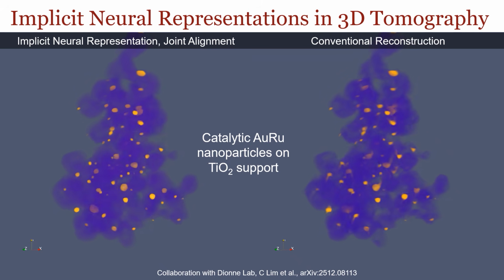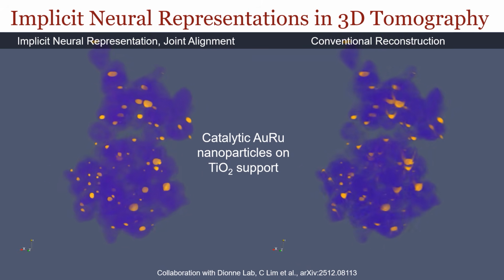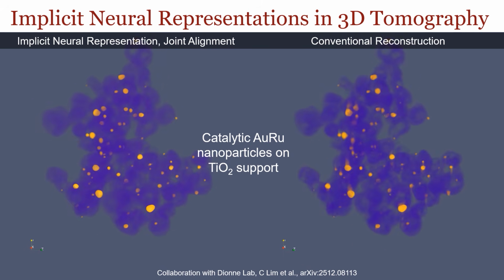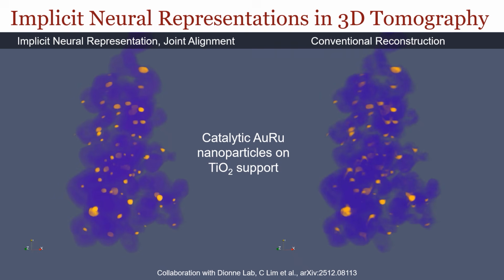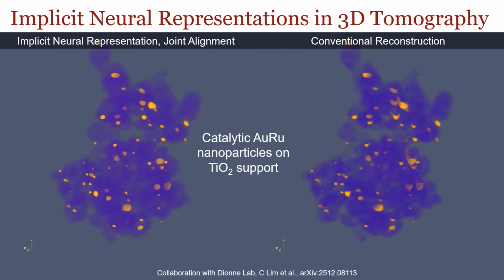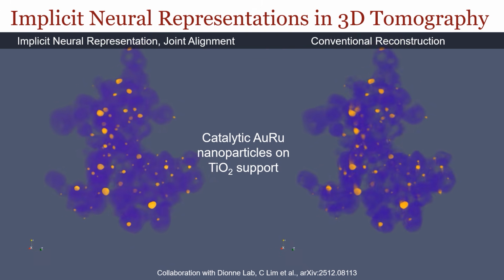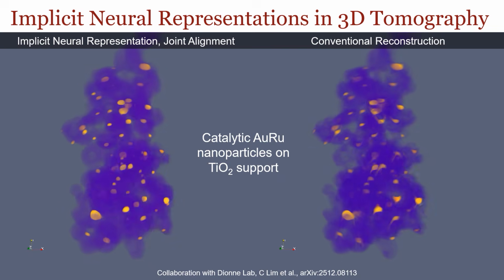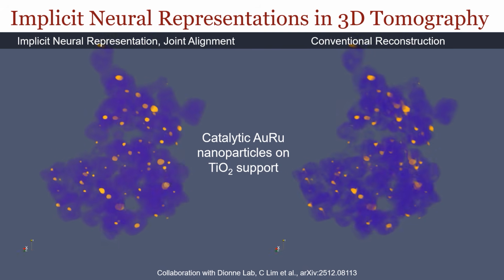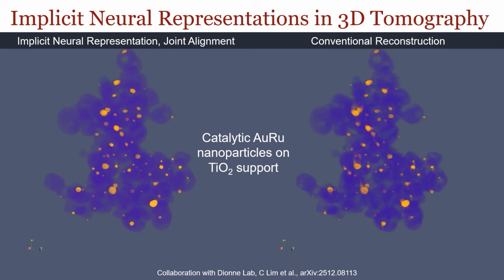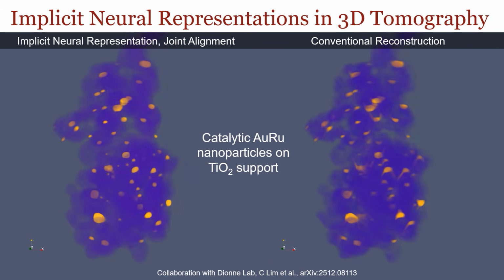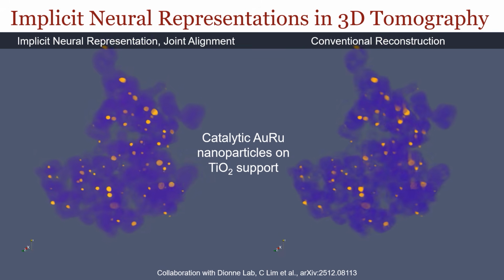And you can immediately see in the conventional reconstruction massive artifacts, right? The particles have these little wings that are sort of taking off. And that's because when you zoom down to the single atomic level, tilting has to be extremely precise. Our stages are mechanical, right? So you're going to have a 1 degree error here, a 2 degree error there, and this micro misalignment leads to these artifacts in the reconstruction.